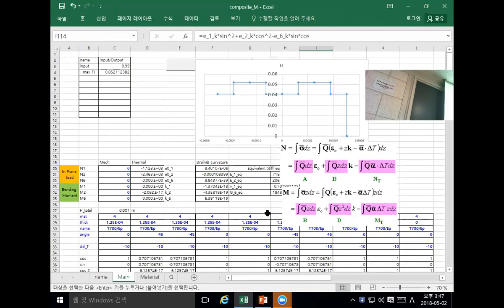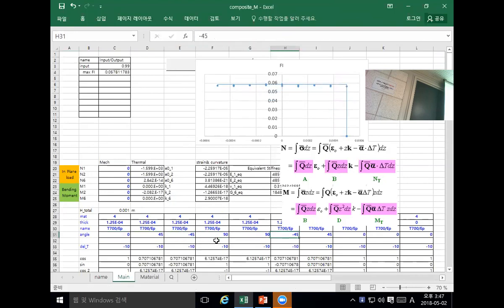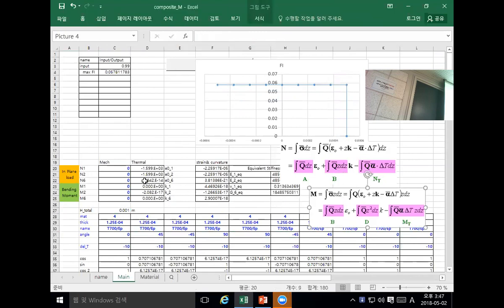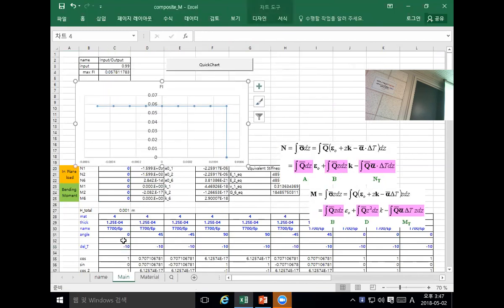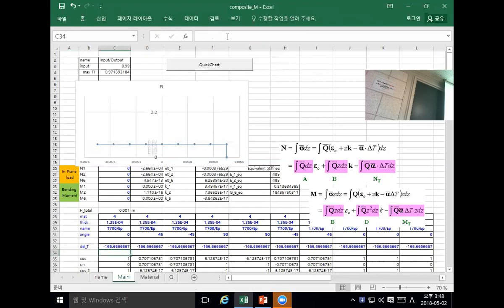Now let's take a look at this all quasi-isotropic laminate, and the ply we have is 1 millimeter thick, total 1 millimeter thick, right? 8 plies, and we have no mechanical load. Let's see how much temperature drop would cause this material to fail. Well, it's 0.06, 0.06. A 166 drop, the material will fail due to the thermal stresses.